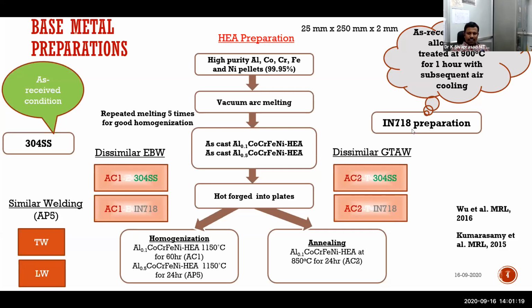And Inconel 718 we have prepared in a particular method before welding was started, such as solutionizing treatment. Prior to that, we prepared the high entropy alloy ourselves; we did not procure it. We took high purity aluminum, cobalt, chromium, iron and nickel pellets or chips, metal pieces, everywhere 99.95% minimum purity. All these things were vacuum arc melted.